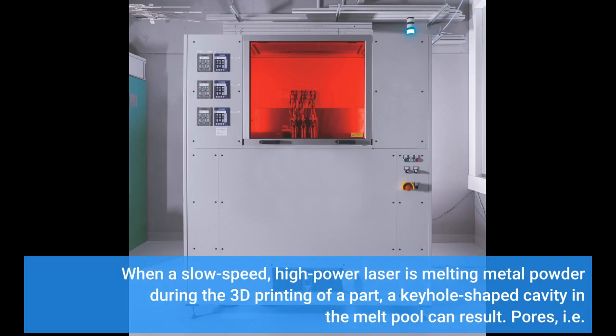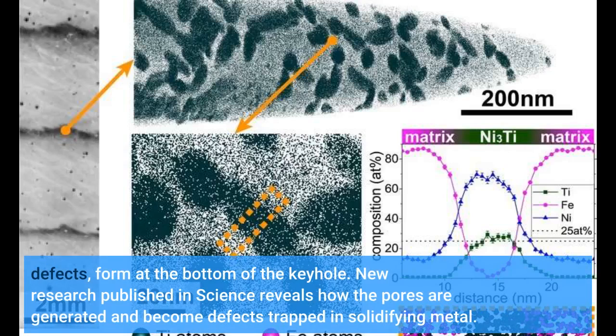When a slow-speed, high-power laser is melting metal powder during the 3D printing of a part, a keyhole-shaped cavity in the melt pool can result. Pores, i.e. defects, form at the bottom of the keyhole. New research published in Science reveals how the pores are generated and become defects trapped in solidifying metal.